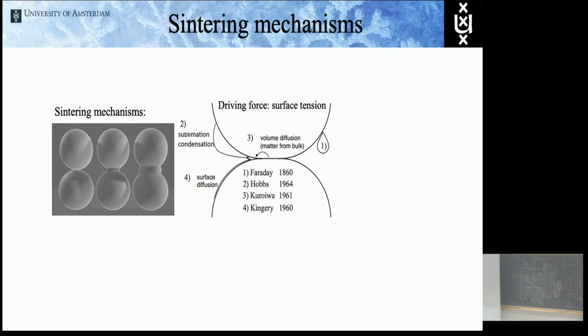So if we have these spheres that sinter, or my little scratch that heals, there can be different mechanisms for the transport. There can be a water layer, a pre-melted layer that flows simply under the action of the surface tension into the gap, and that then freezes and makes the neck grow. The second possible transport mechanism is that ice molecules evaporate and redeposit where they are happier, namely in the gap or the crack. It would be possible in principle to have matter arriving from the bulk and going to the surface, and then the fourth possible mechanism is molecules diffusing over the surface and having a higher probability of sticking here than remaining over there.